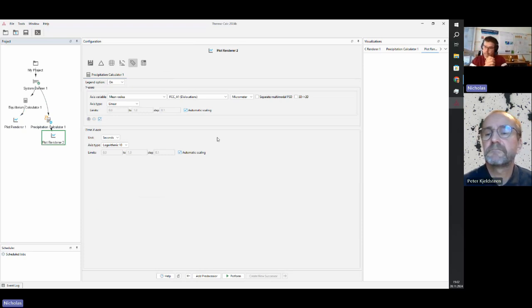Yeah. And this, by the way, is one reason why we are starting to include elastic constants into our databases, right? Because the morphology of the precipitates depends basically on the elastic constants of the matrix, and that's one of the driving forces for the morphology. So that's one reason why we're starting to look at elasticity.